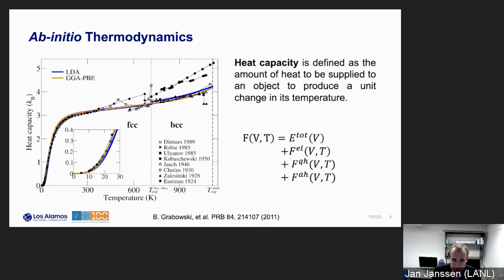Based on this, we can then simulate full elements and really the heat capacity of bulk samples, and have not only a qualitative but really quantitative agreement with the experimental results. And that's very important because we could say, okay, the experiment already gave us the numbers, yes, but in particular here for the BCC phase, the larger scale databases previously trusted this upper branch here. And only with our theoretical predictions, we were able to convince them to then also follow this lower branch.